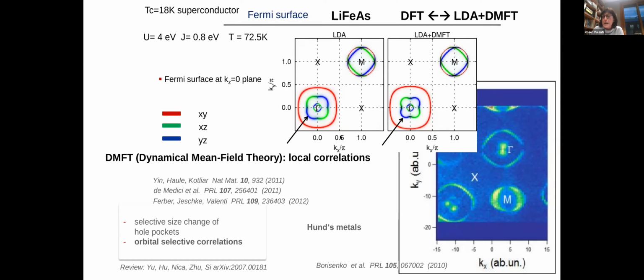So for instance, going back to the Fermi surface description, these are the LDA calculations, and these are LDA plus DMFT. We see this trend of renormalization of these inner hole pockets getting more shrunk, as is seen in experiment. But the most important result of this type of calculation is the fact that the correlations are orbitally selective. So different orbitals show a different degree of correlation.